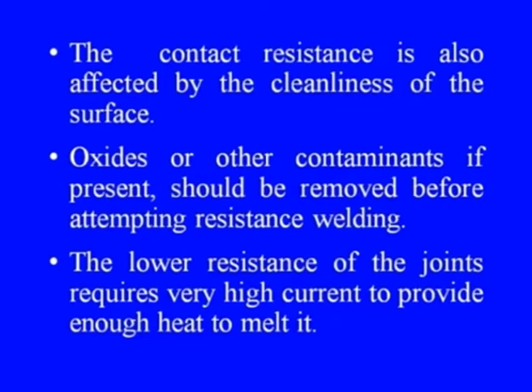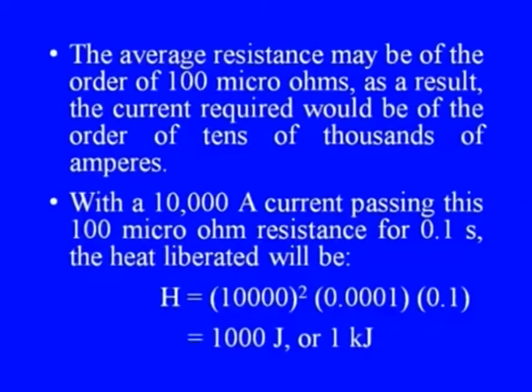The contact resistance is also affected by the cleanliness of the surface. Oxides or other contaminants, if present, should be removed prior to attempting the resistance welding. The lower resistance of the joints requires very high current to provide enough heat to melt it. The average resistance may be of the order of 100 micro ohms. As a result, the current required would be of the order of tens of thousands of amperes.